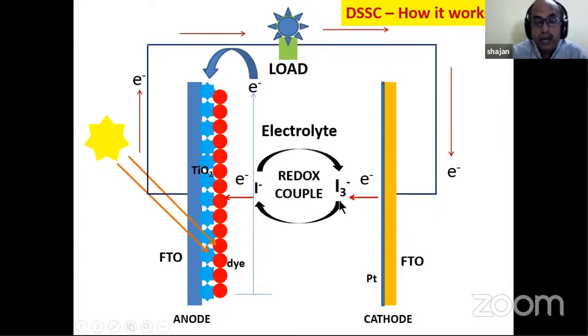At the same time, the dye has to be regenerated by the coupled redox electrolyte, through the electrolyte. And also you see the titanium dioxide is over the FTO, and immediately above that the dye is there, and immediately above that the electrolyte is there. So everything is interconnected. Instead of the electron diffusing into here, the electron may come back to the dye itself. So there are several photophysical events happening.